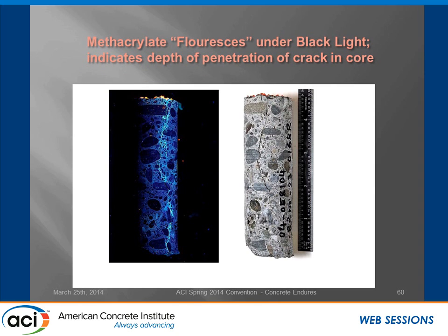How do we treat our cracks right now? We have a product called methacrylate that we apply topically to the bridge deck, and as this core shows, under black light, it fluoresces where that crack is. So you can see that crack goes all the way down through that core.